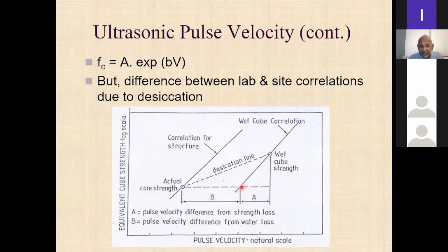However, in the structure, when you do the pulse velocity here, you are doing it under moist condition. So the pulse will travel fairly quickly through the moist concrete. In the structure, especially if it is something like 12 or 15 years old, you will have very old concrete, and I am assuming you are doing it when it is dry. So then there will be a loss in the pulse velocity because of the desiccation, because the water is not there compared to what you have here. So this is called the desiccation line. I think this is from an early paper from a fellow called Thompson.